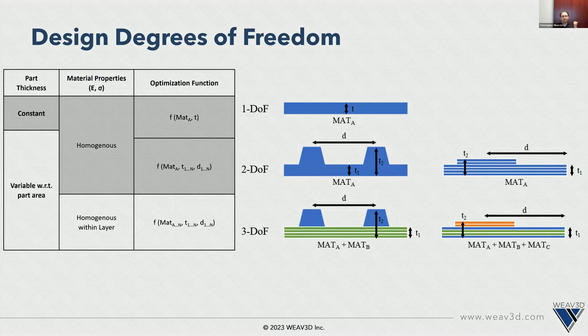This is things like back-injected laminate structures, or things like composite laminate stack-ups with cores or other mixed materials, where you might have a ply of glass fiber and a ply of carbon fiber and then a core, and so on and so forth. So you're now looking at being homogeneous within each layer of the structure, but you are effectively heterogeneous through the thickness of the structure. So you have some different materials potentially in the structure. Each of those different materials can have different thicknesses in different areas, but within their own layer of the structure, they're one material.